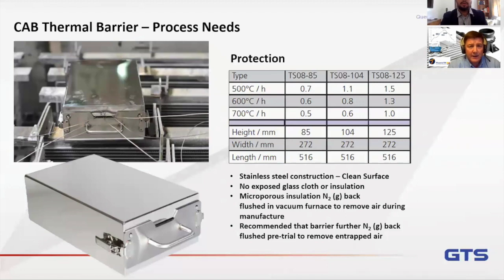The barrier is designed so that in the manufacturing process, it's actually heated in a vacuum furnace, and it's flushed so that any air inside the material is removed. And you can also, if you want to, flush the system before each run to backfill with nitrogen gas. So you're eliminating the risk of any contaminant, oxygen or air inside the barrier escaping as it travels through the furnace. That's a good tip.